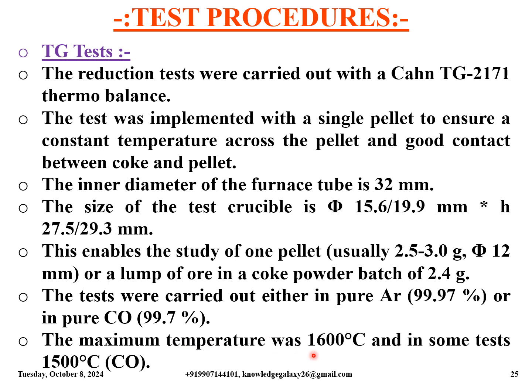The maximum temperature was 1600 degrees Celsius, and in some cases 1500 degrees Celsius temperature was incorporated for the carbon monoxide heat. In each test, one chromite pellet was embedded in coke powder, that is 0.074 to 0.149 mm in grain size. The coke was carefully homogenized before the tests. The pellet plus coke batch with the crucible was put in the furnace.